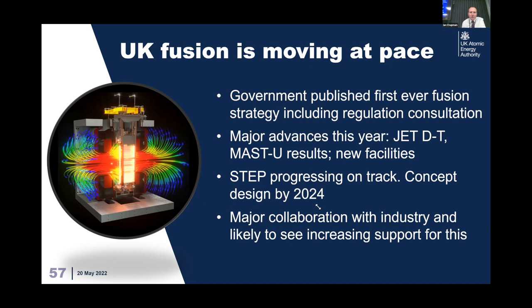Now, I talked about the flaking of the tungsten. That will happen. We know it will happen. Sometimes that tungsten, either by magnetic force or just gravity, could end up just a flake of tungsten going into the core fuel. Tungsten is great for high heat flux, but it's high atomic number. So when it goes into a hydrogen fuel, it radiates the energy because it's really high atomic number. And so that will very rapidly drop the temperature of the fuel, and then the magnets may not be able to react quickly enough to keep the confinement.